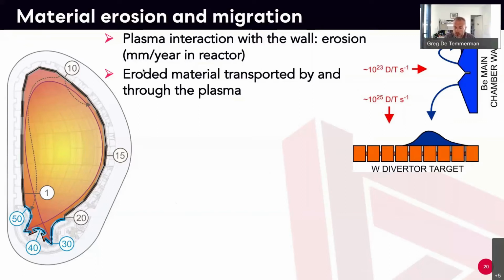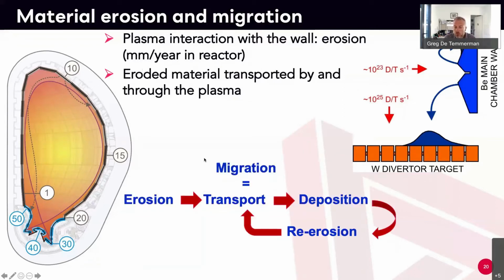But this thickness cannot be infinitely large because you need cooling at the back. You have high heat fluxes, so you have to find a balance between how much erosion you have, how much thickness you can have, and how much cooling you want, and this is pretty tricky engineering. Basically, there is a continuous migration of materials inside the plasma. You erode atoms, they get transported, they get deposited, they get re-eroded from somewhere, they get retransported, and then it's